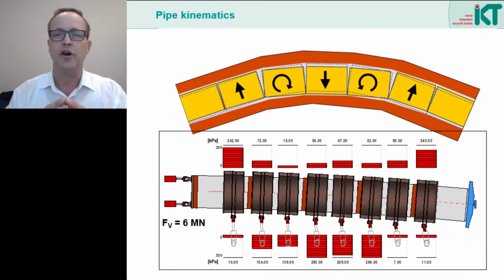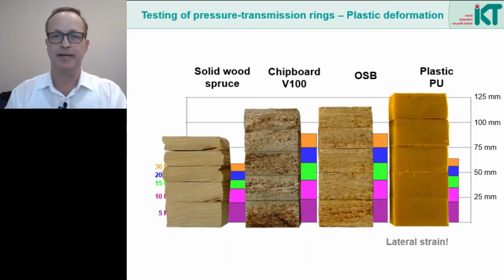We now need to know even more about how the pressure transmission means behaves under extreme loads. Therefore, we have also carried out many investigations in this field, and it was particularly interesting to see how the various pressure transmission means deform in comparison to each other. Here we see test specimens of pressure transmission means which we subjected to typical jacking loads. 5 different load tests were carried out for each material, with 5, 10, 15, 20 and 30 megapascal compressive stress, each with 20 load cycles.